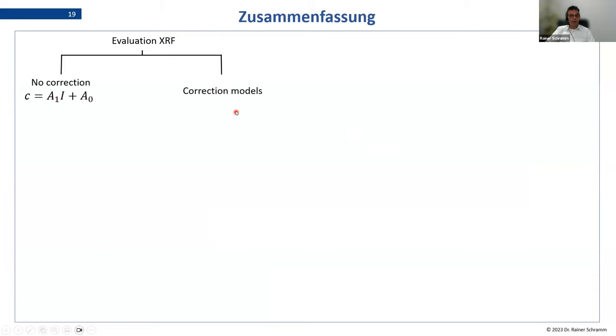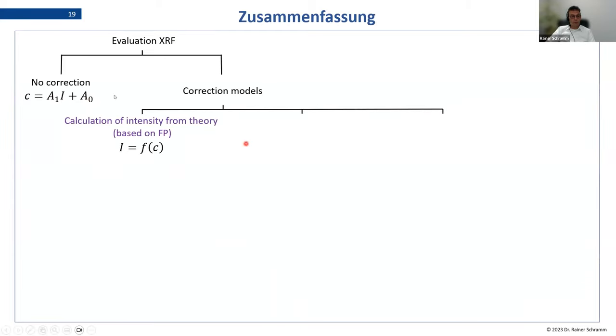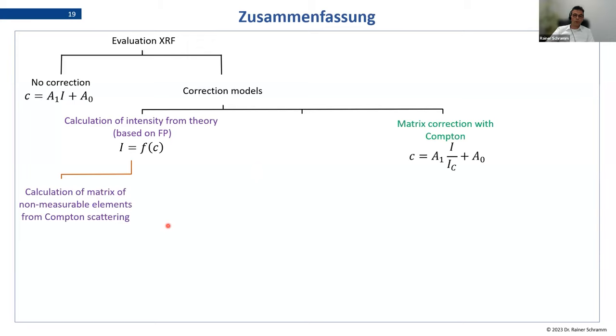But if you need a correction, because there are other elements which are disturbing your calibration element, then you have different choices. First of all, you could go just for a standardless approach, like we have it nowadays in all different kinds of X-ray spectrometer software packages, and just use that to describe your sample, and you get a first quantitative analysis. And this could be also combined with the Compton scattering approach so that even the non-measurable elements could be analyzed as matrix part. Yeah?